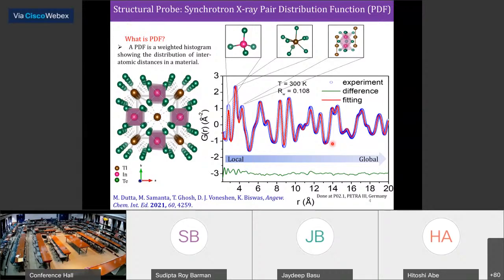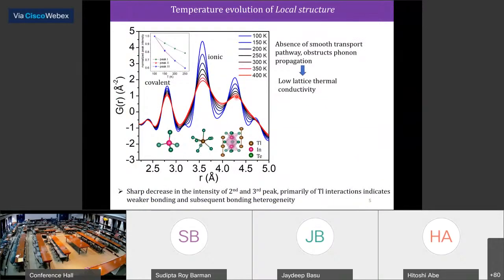So let's see, we have done temperature dependent X-ray PDF from 100K to 400K, and you can see this covalent bonding framework, that is the indium telluride bonding. The intensity does not decrease much, whereas the second and third peak intensity decreases heavily. So that tells basically this thallium tellurium bonding is weak, and thallium can vibrate in that channel. Moreover, this compound has a bonding hierarchy, covalent and ionic bonding framework.